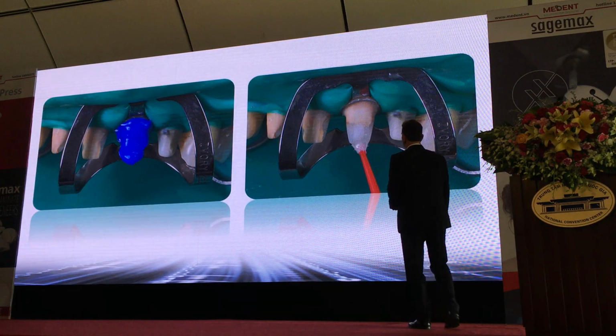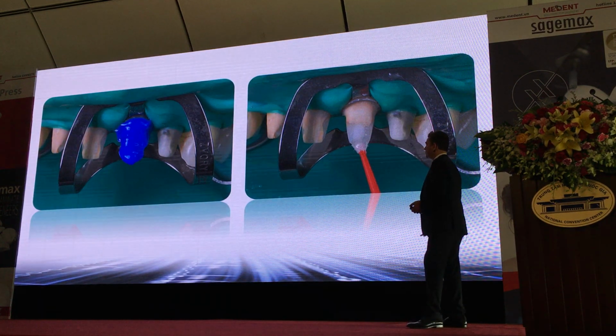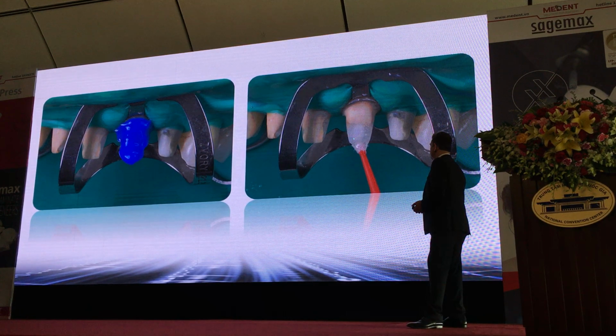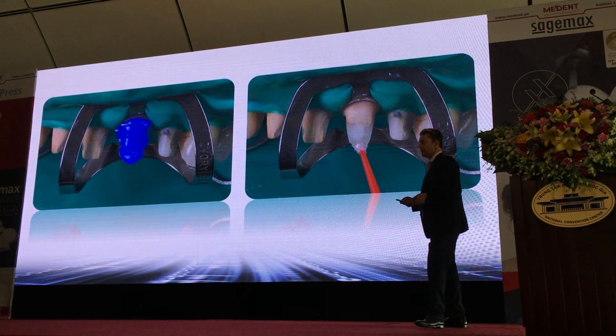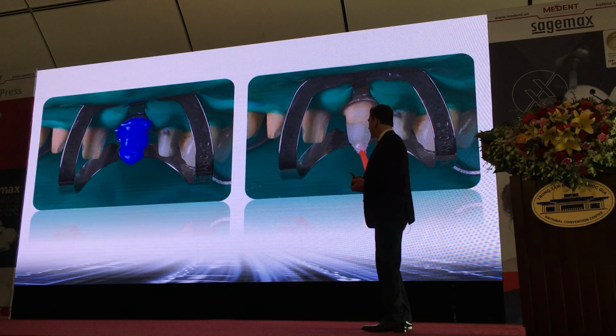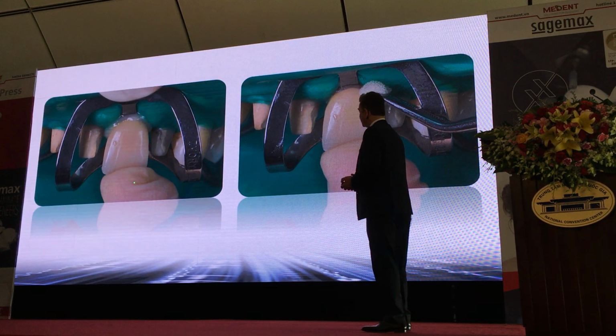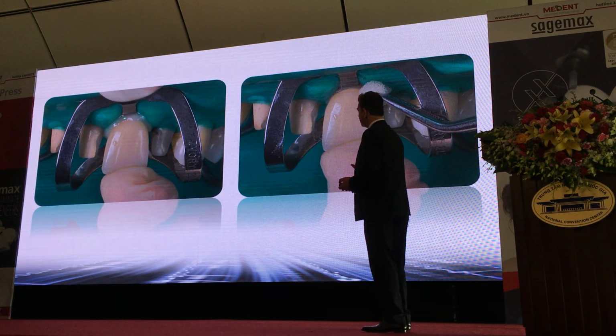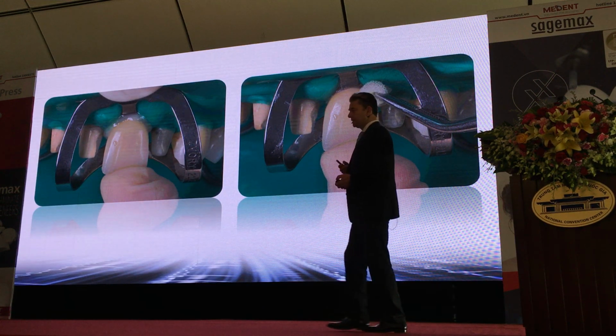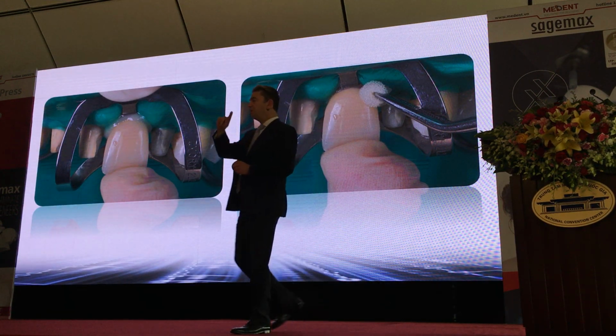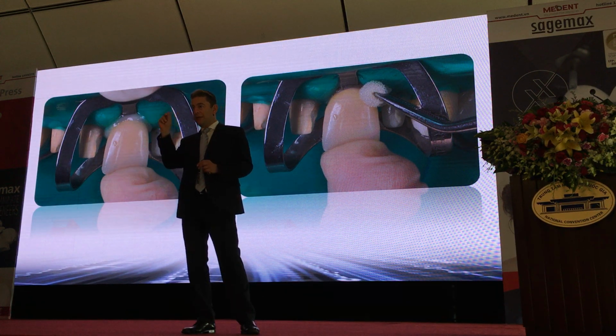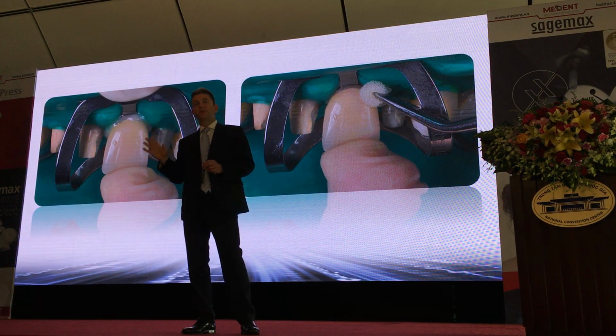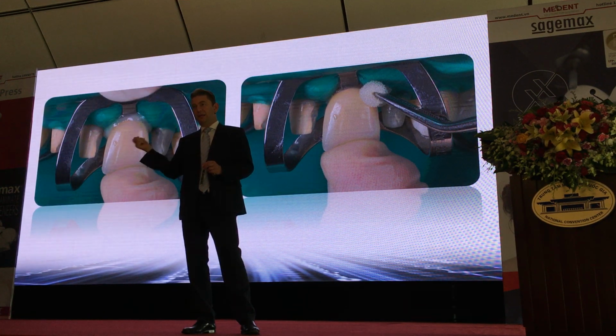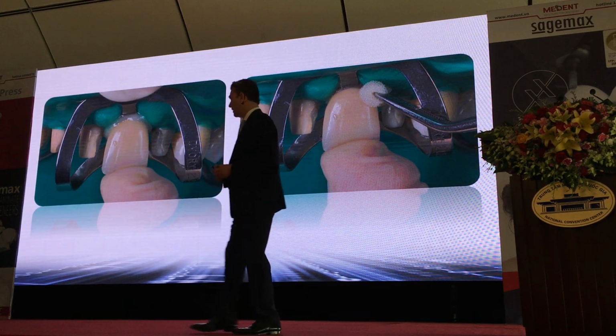Okay, and we apply a bonding agent on the tooth, so we can pre-etch. We use Adhese Universal or Tetric N-Bond Universal. We seat the crown. You can see the excess. Now the question is, how are we dealing with excess resin cement? Of course, we can wipe it with a foam pellet. Some of the cement, you can also light cure for 1 or 2 seconds, and then remove with a scaler.